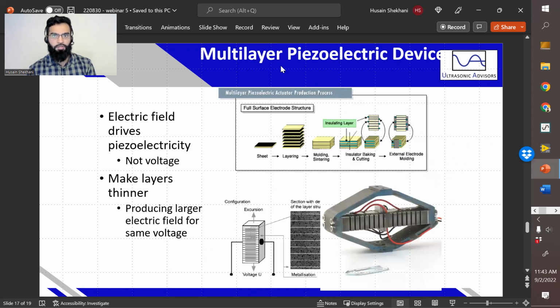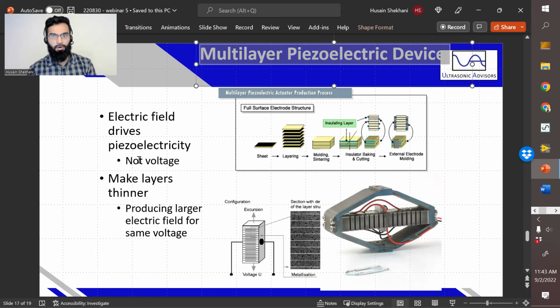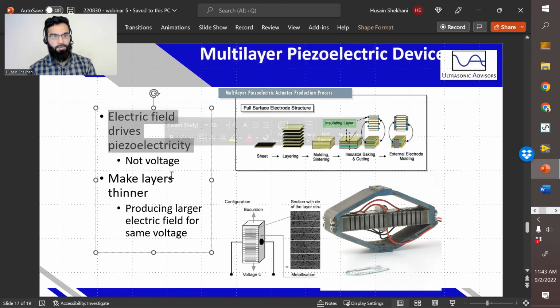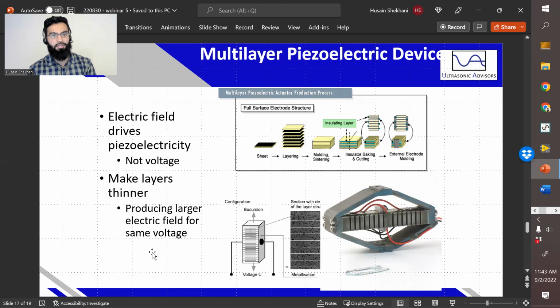In order to get large displacement, you can use multi-layer devices. You layer several or hundreds of layers together, and because electric field drives piezoelectricity, not precisely voltage, if you look at the equations, making the layers thinner provides the same voltage across thinner layers, which is effectively more field, and you can get more displacement. But there's always a limit until the device will crack. So that's what you have to consider there.